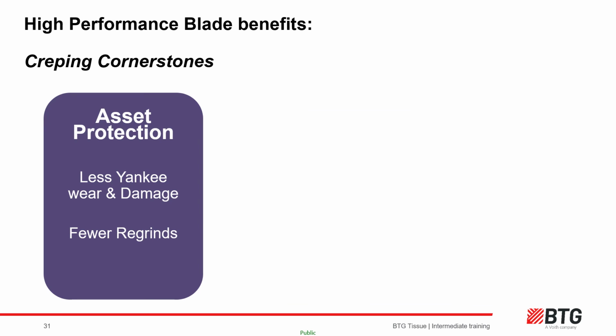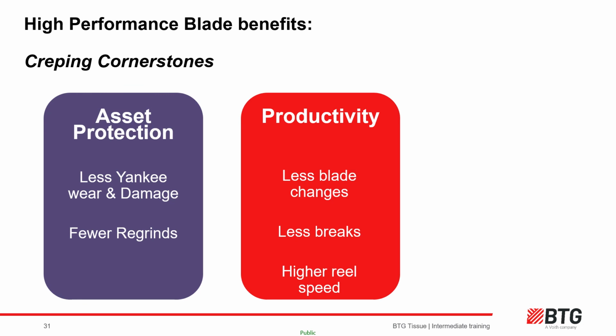And so to finish with the cornerstones of creping and why we use high performance ceramic or carbide blades. They are proven to enhance asset protection through less Yankee wear and damage, including adhesive wear. As such, fewer regrinds are required, which is important on a cast iron Yankee, becomes more important as the shell thickness is reduced, and is massively important on metallized surfaces. In terms of productivity, there are significantly less blade changes, meaning less UTM and more machine uptime.